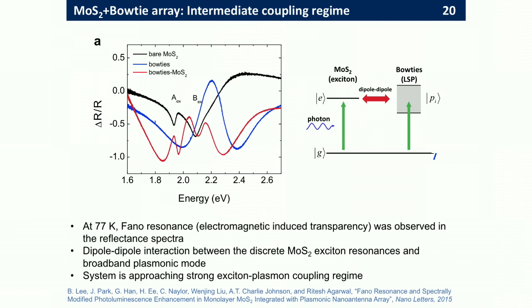But as we started to improve our materials and our fabrication, something very interesting started to show up. Let me explain. This black curve is the reflectance spectroscopy of just bare MoS2, so no metal, no plasmonic particle. You see very sharp excitonic lines corresponding to what are called the A and B excitons. The blue curve is the reflectance spectrum of a plasmonic lattice. And when this plasmonic lattice mode starts to come close to, let's say, the A exciton, the hybrid system shows this very interesting asymmetric line shape, which is what is called a Fano line shape.